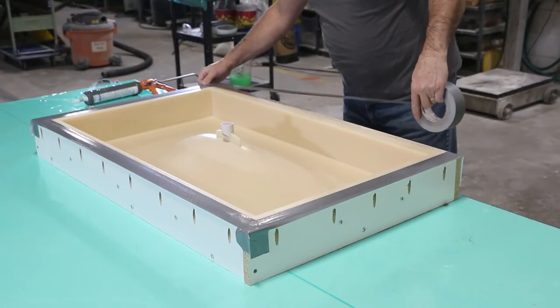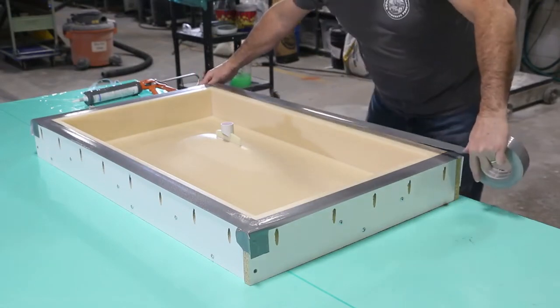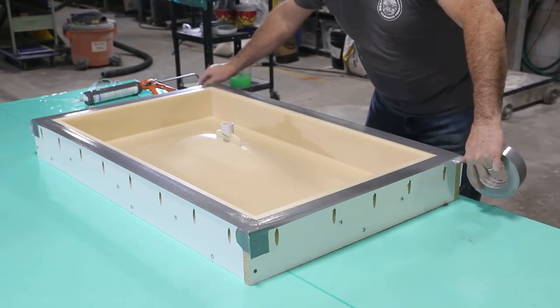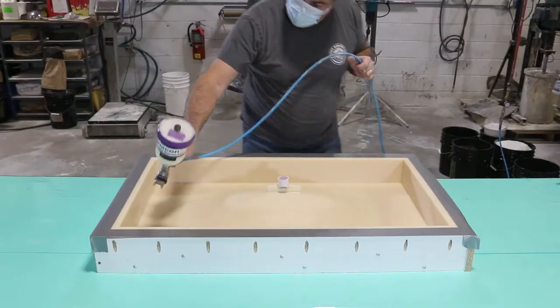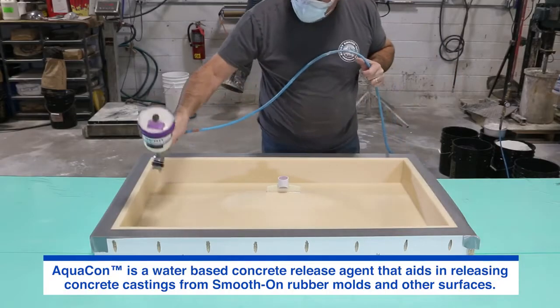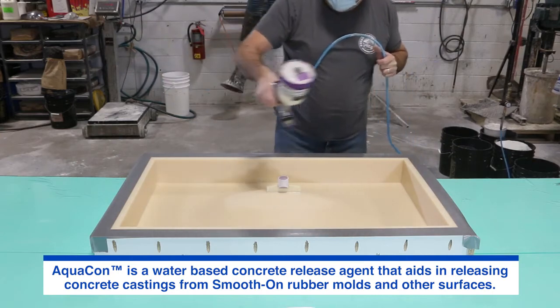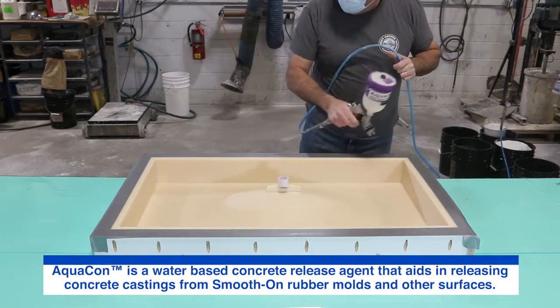Using tape, I covered the top edge where the mold box and mold meet in order to protect concrete from falling into this area, which may deform the mold. Apply Aquacon release agent to the mold with a light spray, being careful to cover evenly.